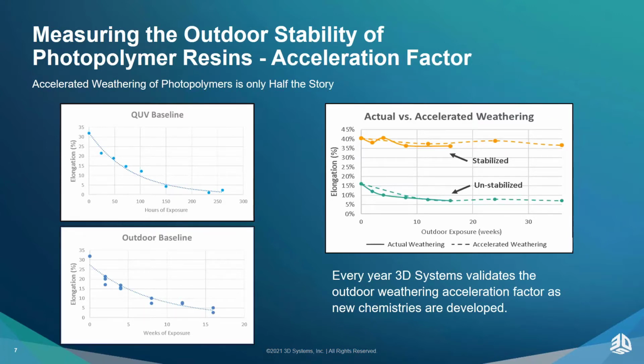In those cases, over the course of several years, we characterized and measured many different materials and plotted them relative to what we were seeing in our QUV. It was through that course of several years that we were able to generate an acceleration factor internally that allows us to transform our hours in the QUV into weeks, months, or years of actual outdoor data, which is really key and beneficial for the customers, because hours in QUV are really not relatable versus understanding that 200 hours in the QUV equates to 5 months